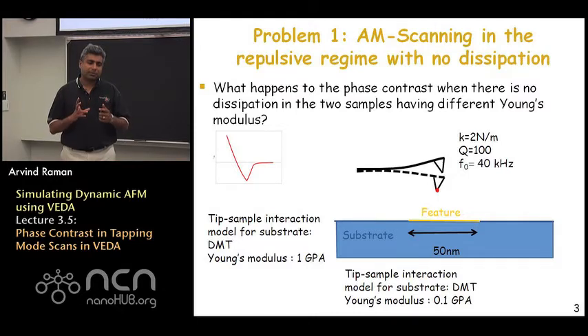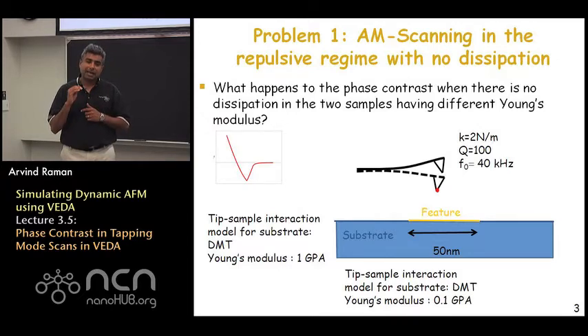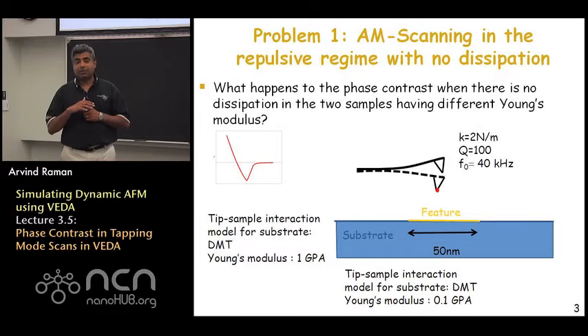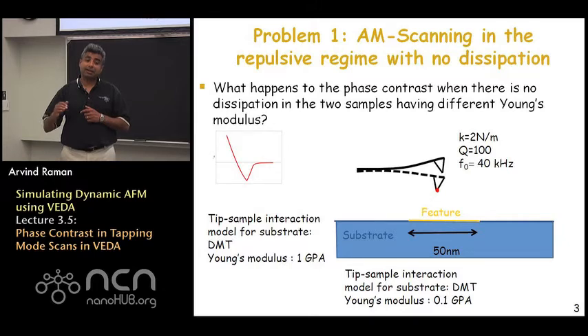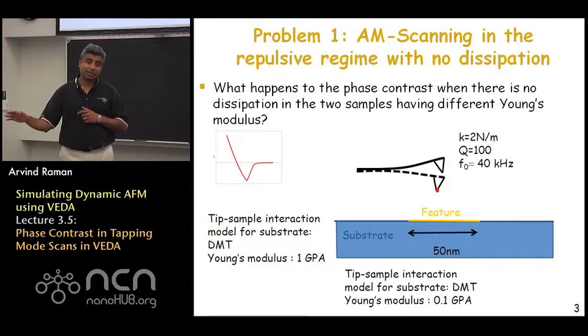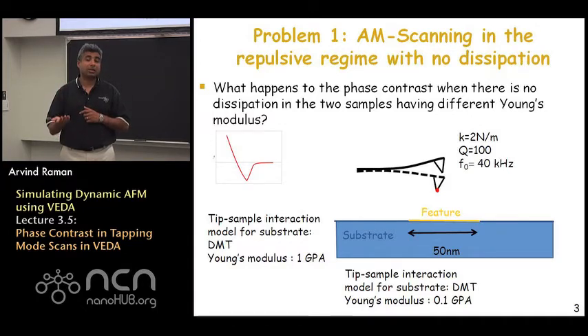Some of the two main conclusions we had when we did tapping mode phase contrast imaging were that whenever the phase lag is more than ninety degrees we are in the attractive regime of operation, and whenever the phase lag is less than ninety degrees we are in the repulsive regime. When observing phase contrast in the repulsive regime — where phase lag is less than ninety degrees all over the sample — brighter phase lag corresponds to larger dissipation. On the other hand, if the image is taken entirely in the attractive regime where phase lag is greater than ninety degrees, the darker parts correspond to greater dissipation.